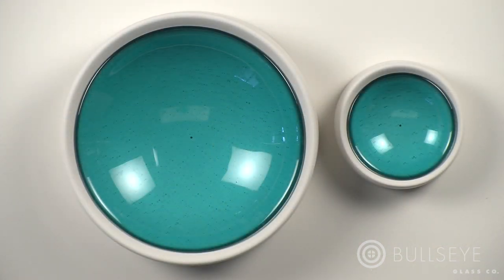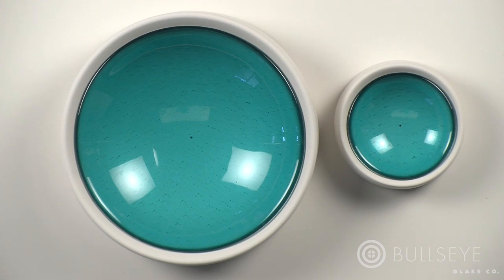Although these ball surface molds are similar in form, the larger one will slump with less heat work because the greater mass of unsupported glass will bend sooner. The smaller form will need additional heat work to conform to the mold.